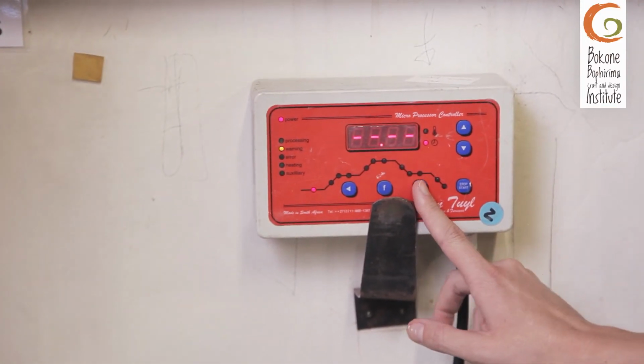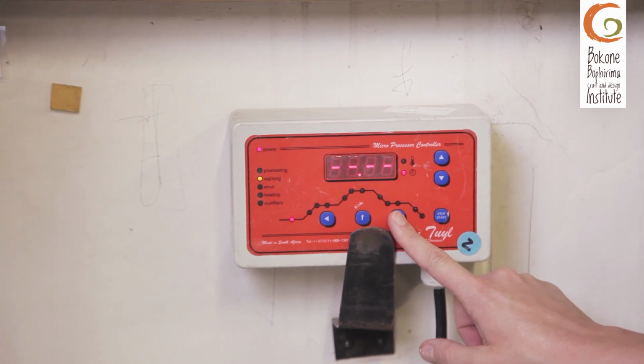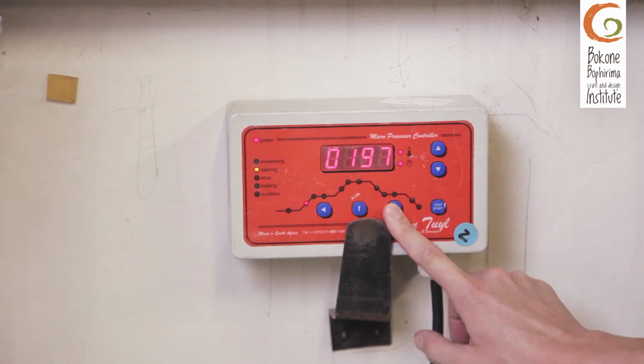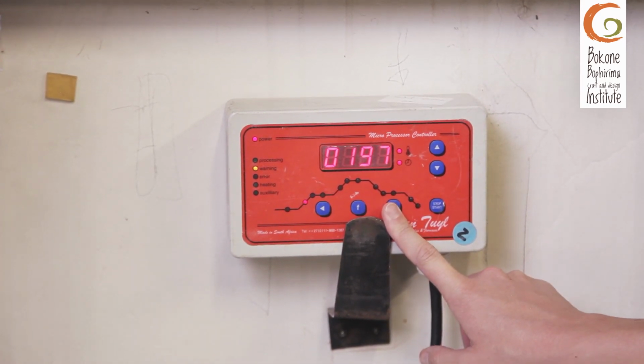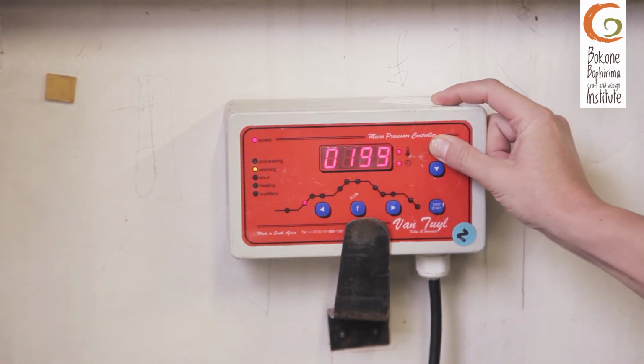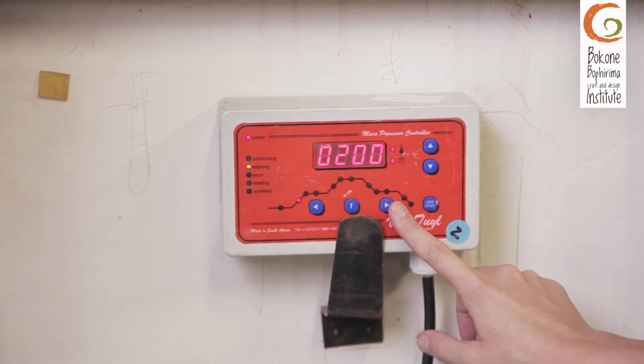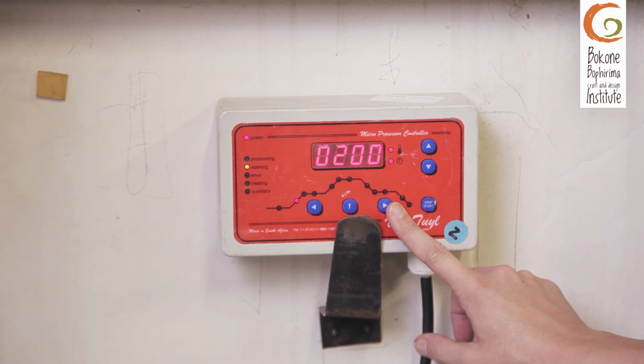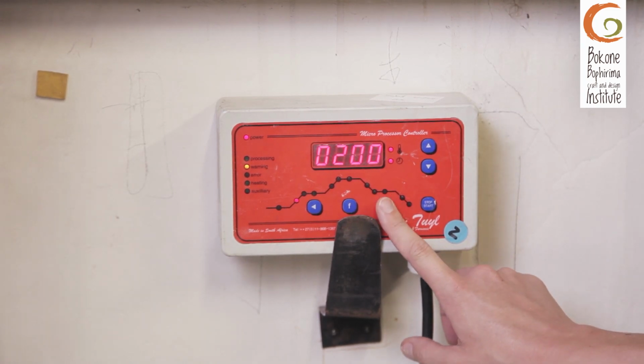We are not using a delay because we want our kiln to start firing immediately. And here we are going to take our glass up 200 degrees an hour. I'm taking it up not too fast because I'm fusing two pieces of glass together, so I want to ensure that it goes slowly here.